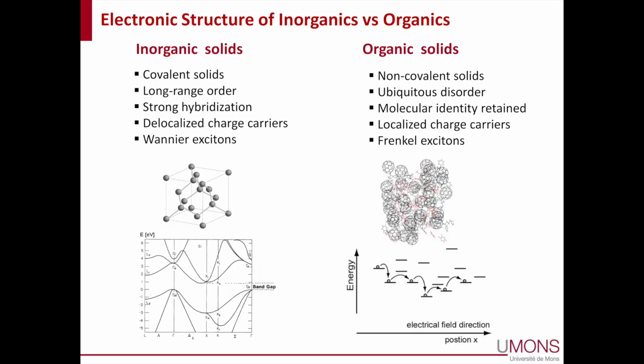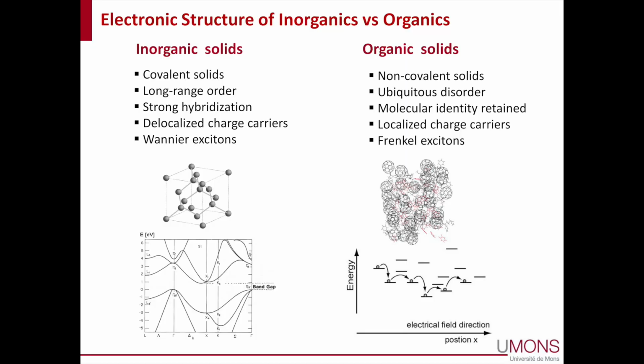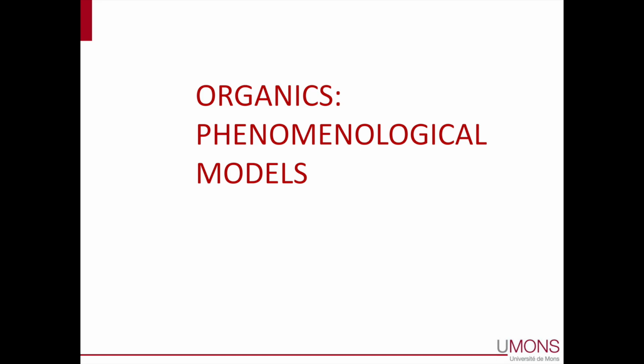So let me start with organic systems. When you think about organic materials, you tend to think that these are really soft materials, and their disorder is ubiquitous, as we just discussed. There's hardly any long-range order. We are talking about very weak interaction between molecular units. That gives rise to Anderson localization or dynamic localization because of coupling to all sorts of phonons. In contrast, inorganics should sustain delocalized, extended states, delocalized wave functions, and give rise to much higher charge carrier mobility.